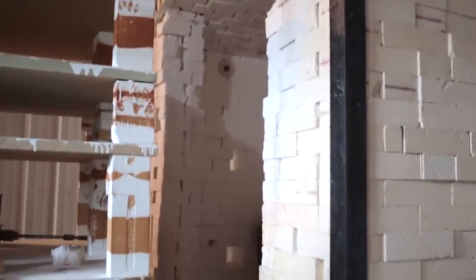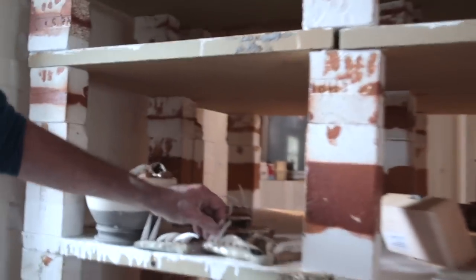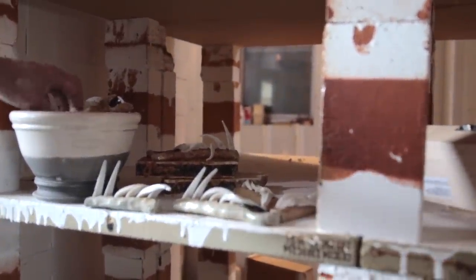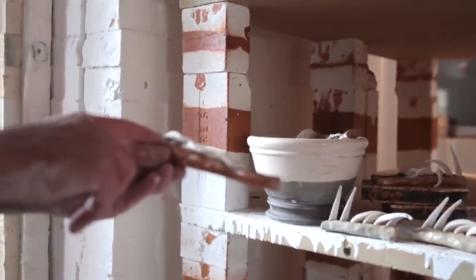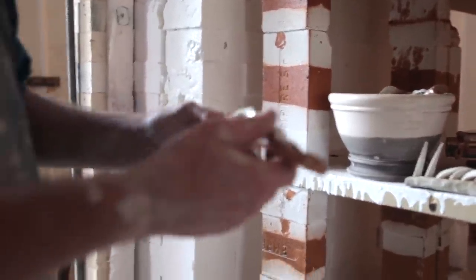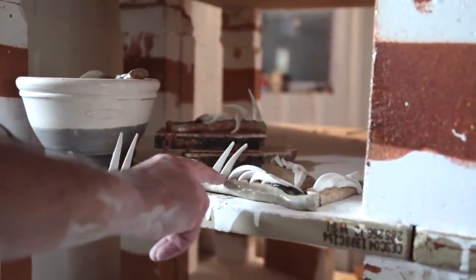This is the big gas kiln that I built probably in the early 2000s. We did a lot of production firing, possibly for Smith & Hawken and other wholesale customers. These are called pyrometric cones and they melt at specific temperatures — that's the guide in the kiln to tell you how hot you got. This cone 11 melts at probably 2375°F. What I'm going for is cone 10, which is about 2350°F. So you can see this was a hot spot, and these were colder spots — cone 9 is maybe 2300°F.